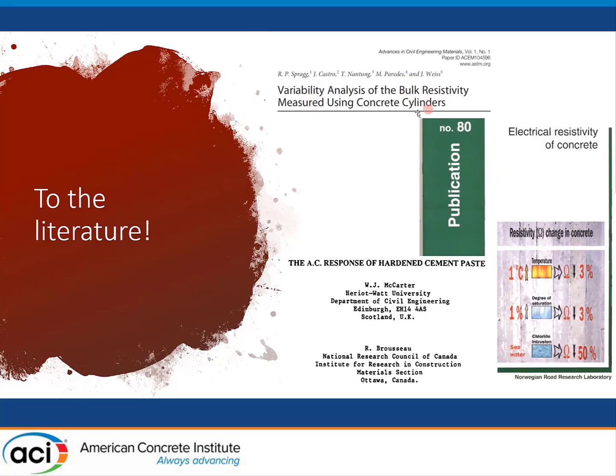In this extensive study looking at bulk resistivity of concrete mixtures, they only used saturated sponges, but they took the sponges and measured the resistance of those sponges separately from the bulk material to kind of subtract out the effect of the actual residual or potential residual impedance from those sponges.